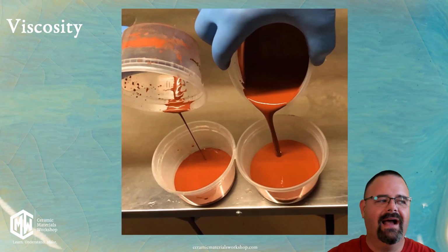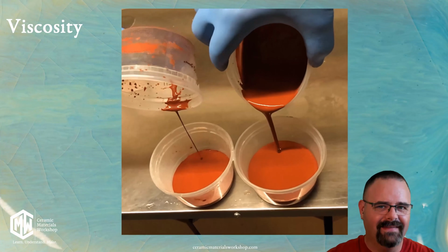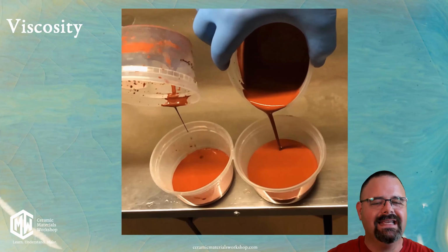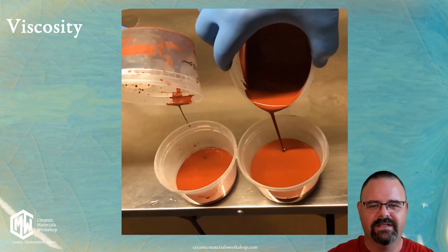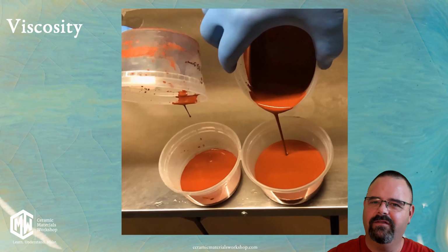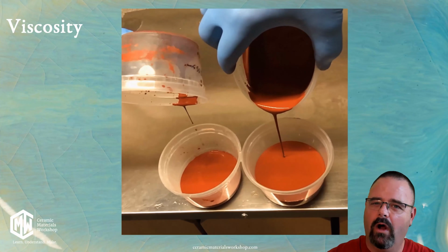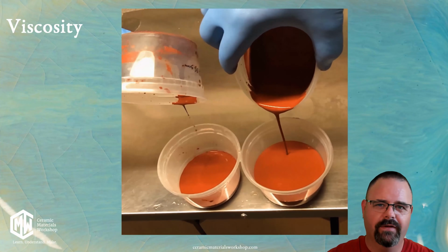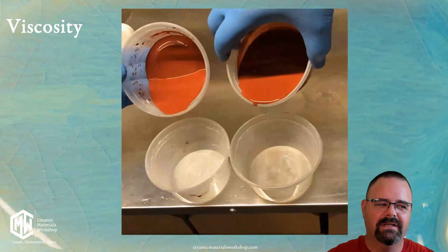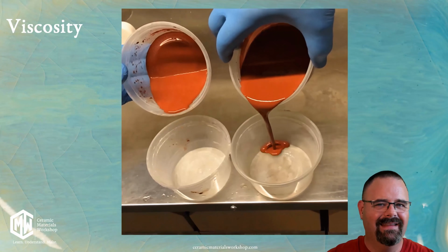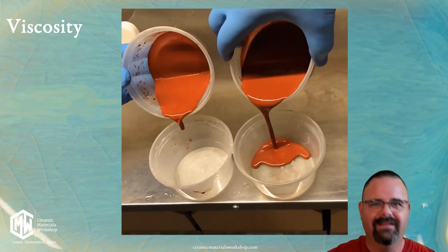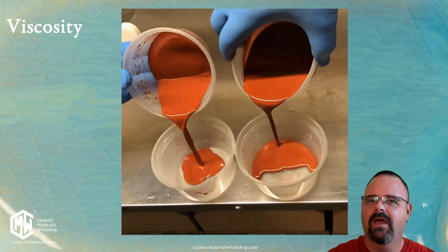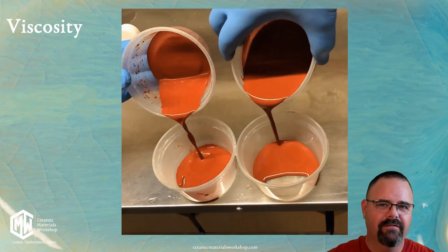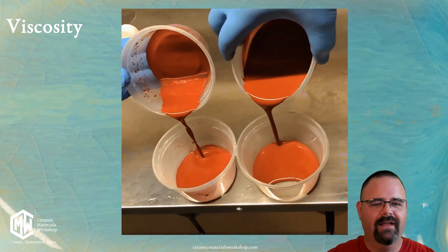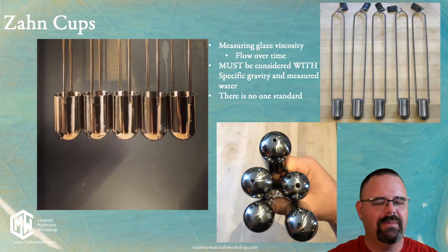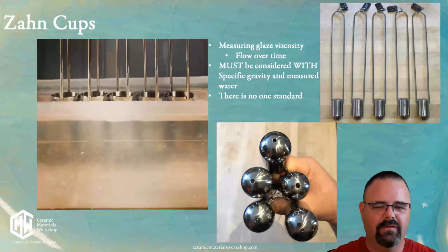But the problem is I have manipulated the viscosity of these glazes. And viscosity is just as important as specific gravity. Viscosity is how a glaze flows, because it doesn't just matter how much the water to particles are influencing the glaze. It also matters how that glaze flows. And that is incredibly important because that's going to affect our dipping, our dip times, and our bisque quality will be affected by viscosity, okay? And viscosity is a pretty simple measurement that most people are ignoring, and we really advocate that people do.